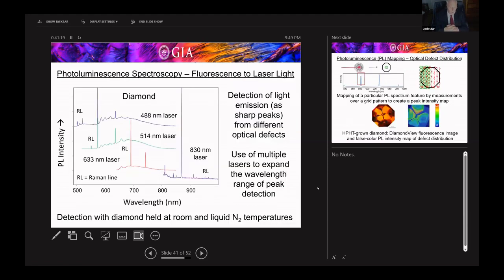We can also do what's called photoluminescence, which is fluorescence to a laser light. This is very valuable for looking at natural, treated and synthetic diamonds. We actually use a range of lasers because they each excite the optical defects in a different part of the spectrum. But again, these defects are a fingerprint of what has happened to the diamond in the earth or during synthesis or during treatment.